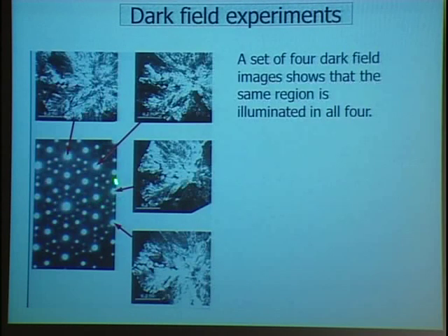A dark field image is when you use one of the diffracted beams, say this diffracted beam, you block out all other beams by an aperture, and you take the image of the crystal, and all the parts that contribute to this diffraction spot will be shining here. And if this was given by one twin, then a little part here will shine, and all the rest will be dark. But that didn't happen. All the crystal was shining here, and using this, everything was shining. So, no twins. Now it's becoming really strange.